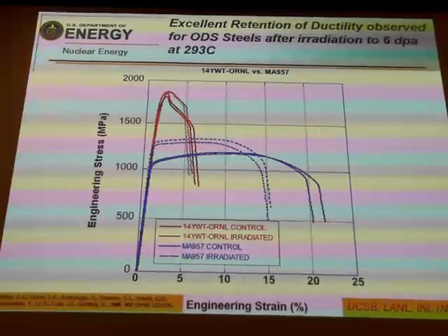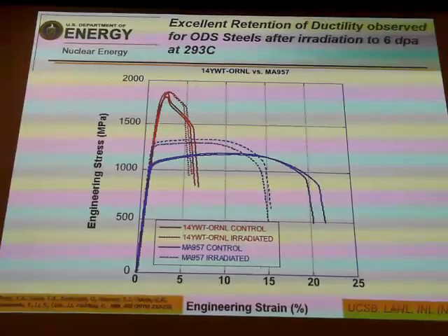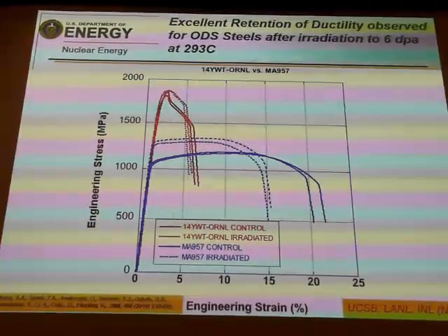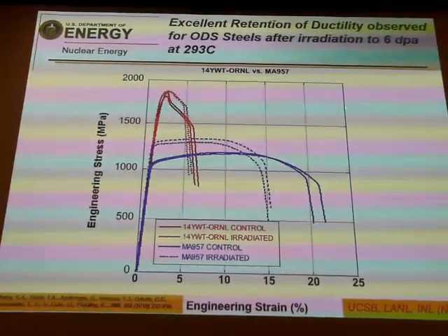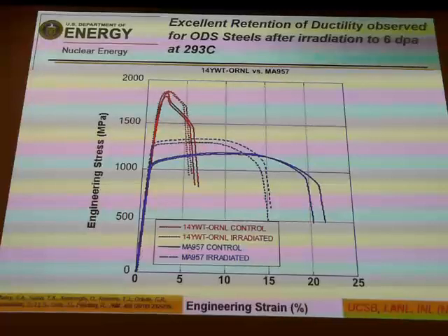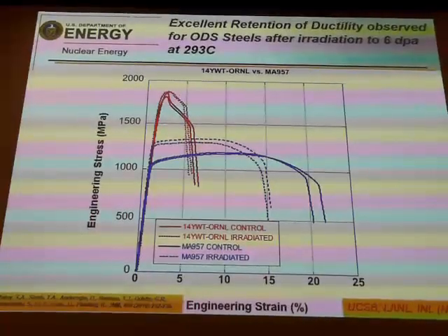And just to point out, why are we looking at these materials? As I pointed out before when I showed you HT9, it maintains its ductility after low temperature irradiation. Now, this is the same irradiation, but we put MA957, an oxide dispersion strengthened steel in there. And we also put some 14YWT that was extremely high strength. This is over 1,500 MPa yield. It didn't get any worse, so it maintained the ductility it originally had after radiation, but I think the real promising one is this MA957, where you can see after 6 dpa at 293C, it's over 5% uniform elongation. And it actually didn't even harden that much.